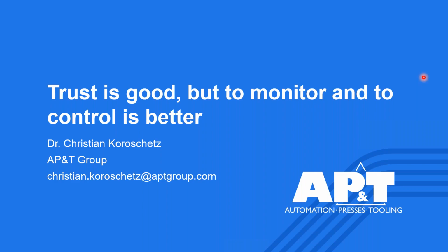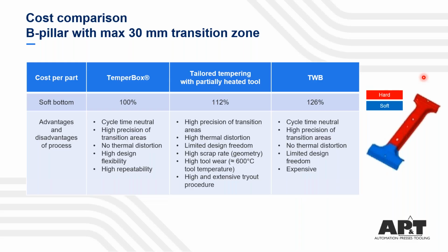I also brought, related to this question, one other slide which compares temper box cost on a typical pressed component with a soft bottom and a hard upper part of the B pillar. If we say the cost for running this part in the temper box is the baseline, then compared to tailored tempering in a partially heated tool, the part is 12% more expensive. And compared to tailor welded blanks, we have a cost increase of 26%.